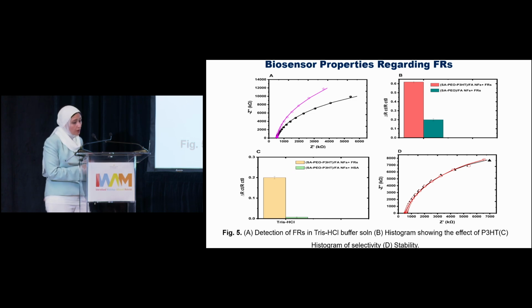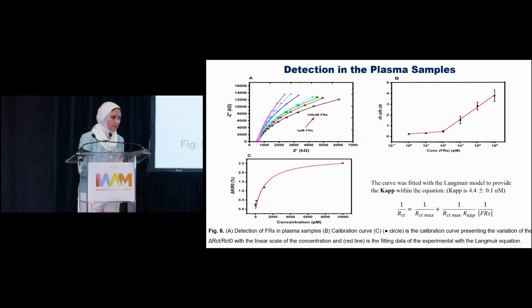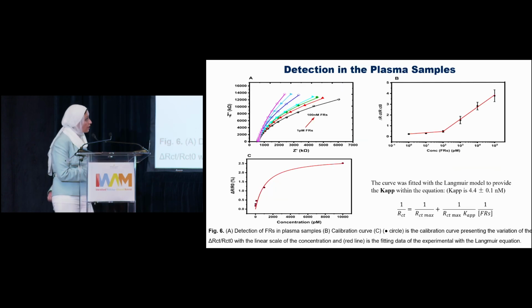Also, we stored our biosensor for 2 months at 4 degrees C to see if there is stability or not, and we obtained nearly the same signal. We made fitting for all the data to extract the value of RCT, which is the resistance of charge transfer. It was nearly the same value. These results encouraged us to investigate our biosensor in human serum plasma.